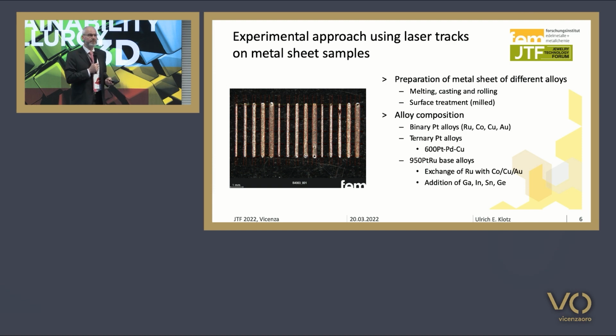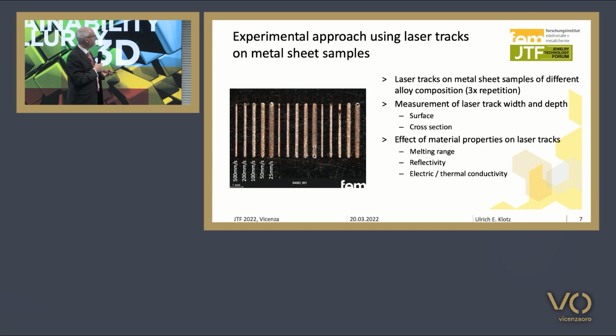So this is our approach using laser tracks. This picture shows you a platinum alloy sheet with different laser tracks. We used different compositions, binary and ternary alloys, and several 950 platinum-ruthenium based alloys. You see the laser tracks have different thicknesses depending on the laser speed. All tests were done at the same laser power, so the smaller the speed, the wider the laser track, because more energy per time unit is applied onto the material. We measured the width of these laser tracks, and also did cross sections to measure the depth of the laser tracks.